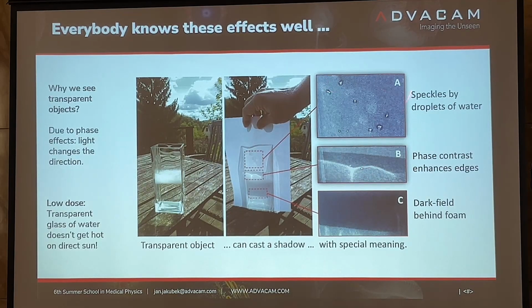And we have also such speckles. If there are some droplets of water on the wall, they basically work as lenses. So if you put your projection plane at the right distance, you start to see these very nice darker regions, and in the middle you would have a very sharp and very bright spot. And all those methods can be used for imaging with X-rays as well.